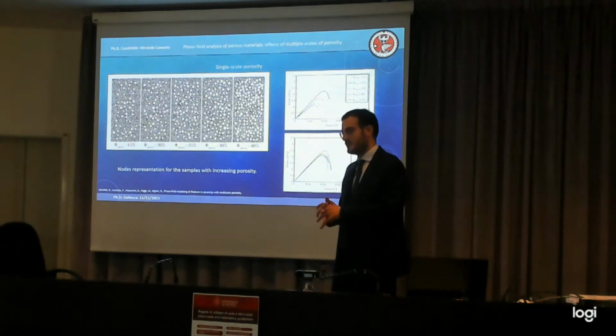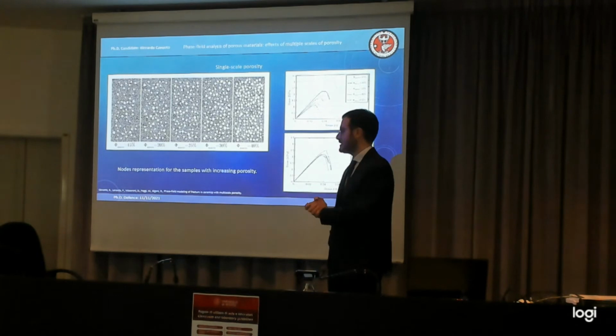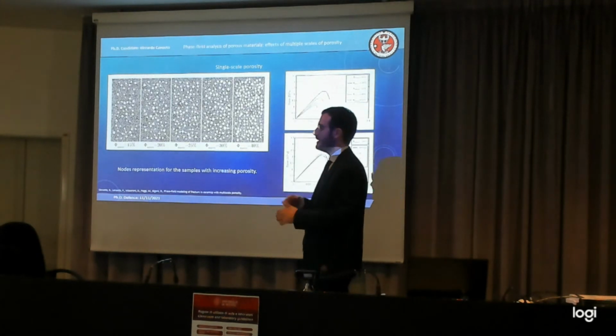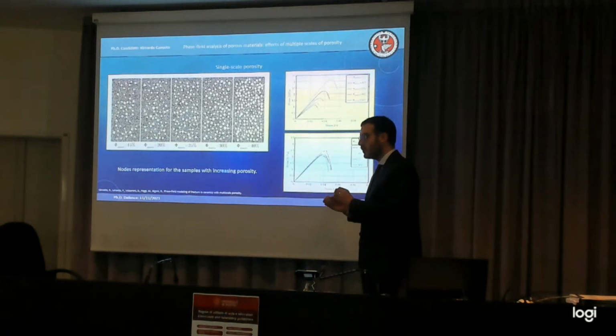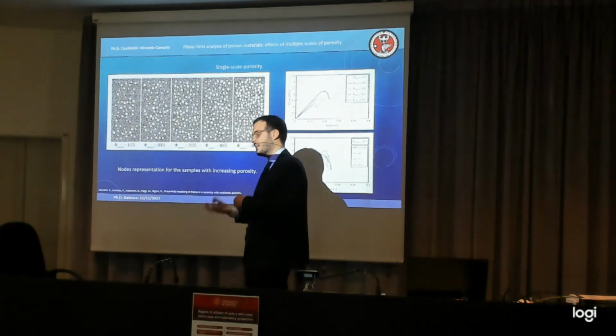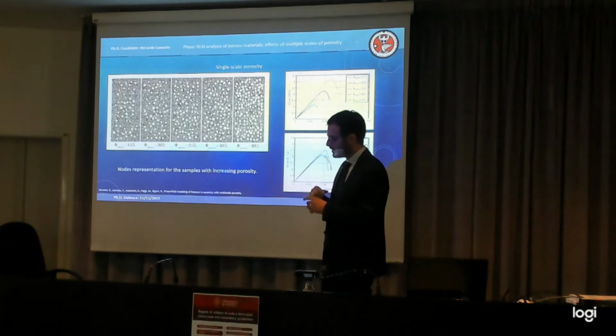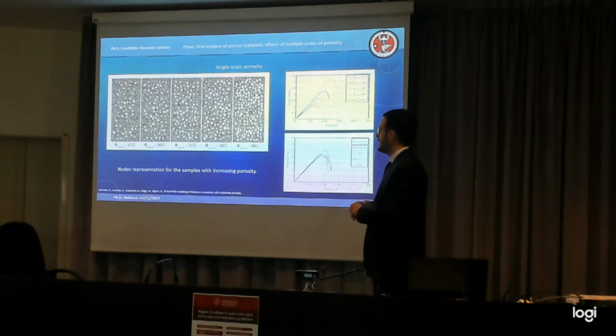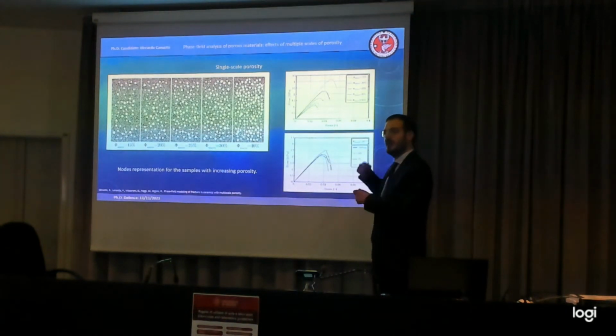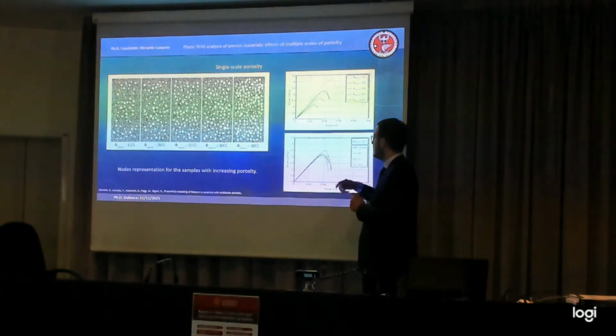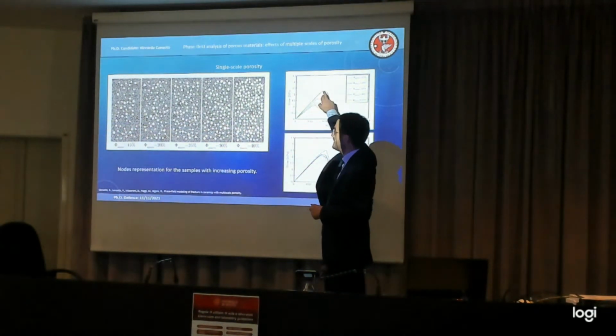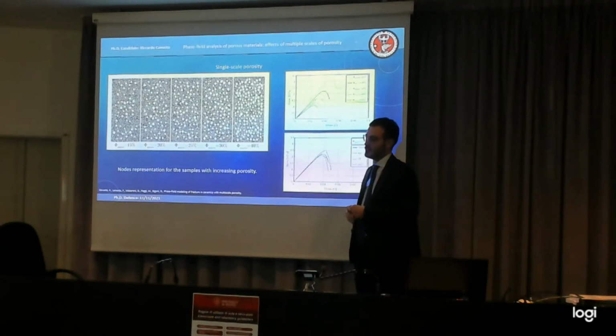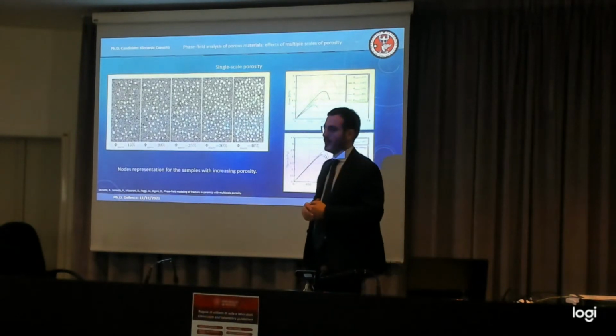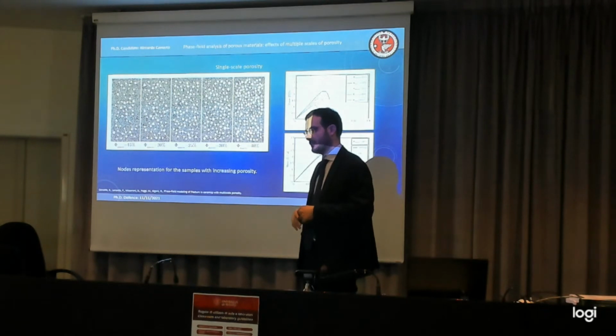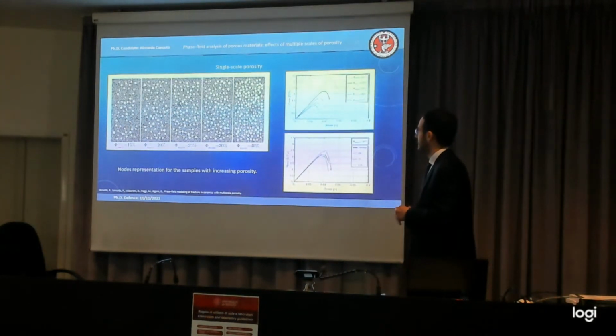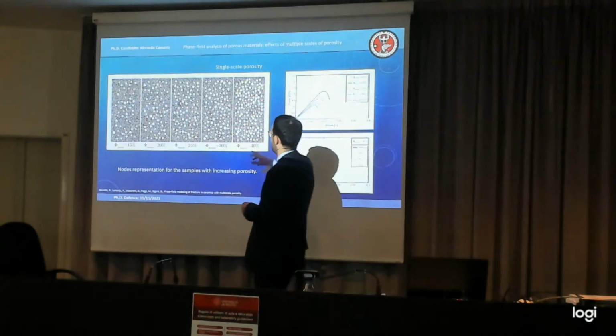You can actually estimate these values by using a very simple one-dimensional model. You take a very simple one-dimensional phase field formulation, and then from the analytical solution for the 1D case, you know that you can expect the strength to increase when you decrease the regularization parameter. You know that the same is happening for G_c, and then you begin from that and you start brute force changing. You try to perform several simulations until the energy absorbed by the total model and the maximum strength reach the level that you want to reproduce. You did it manually or by means of an optimization procedure? No, we did it manually. It's the fastest way. The simulation can be very, very slow, especially for this kind of problems.